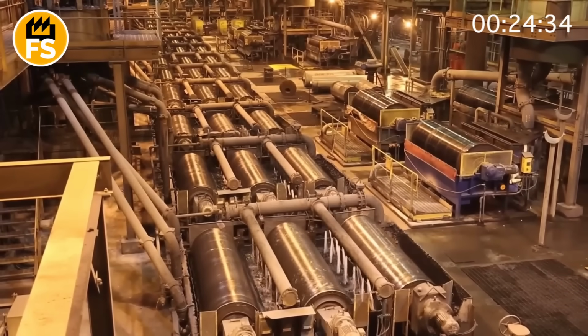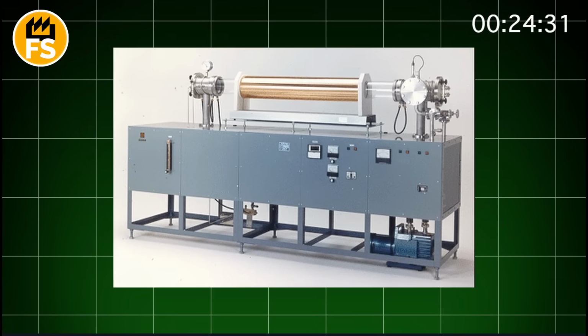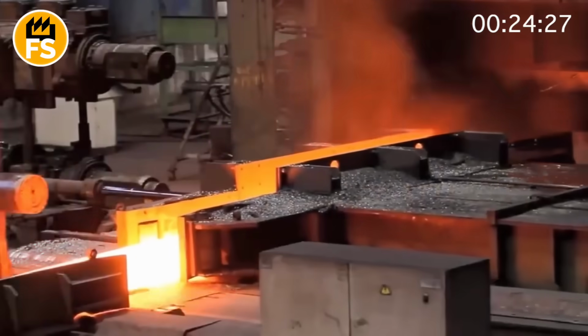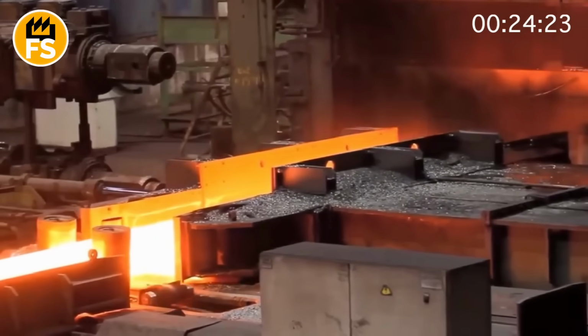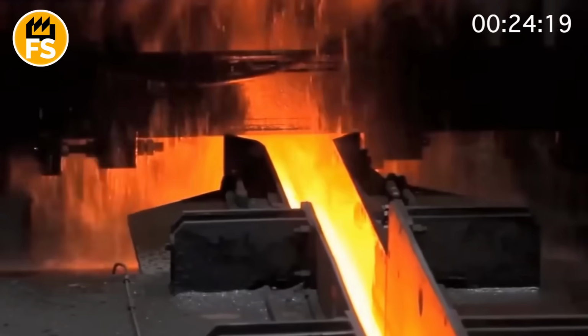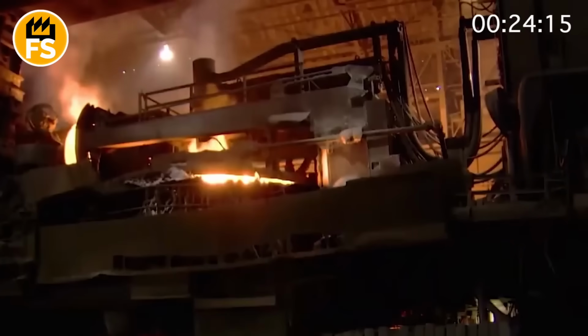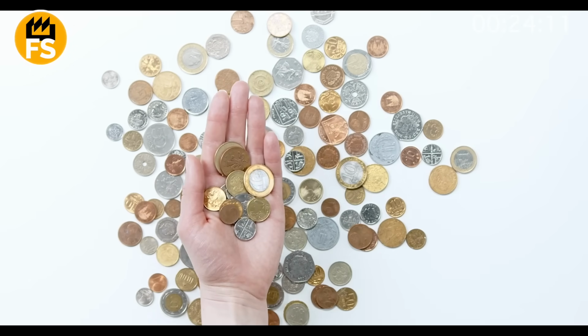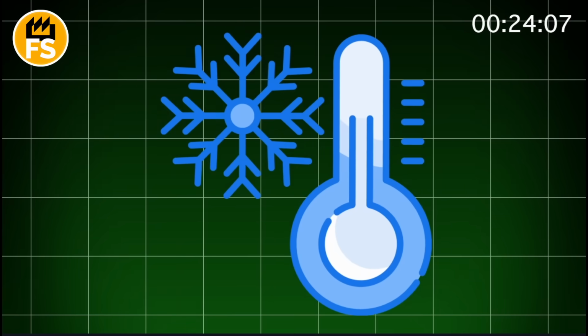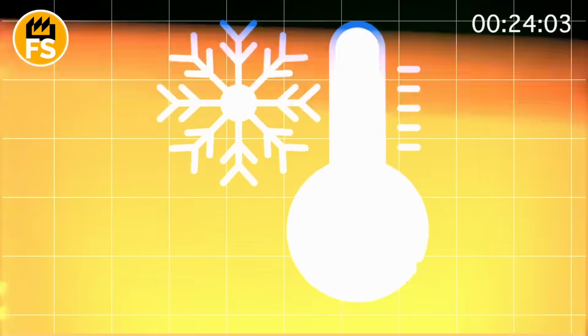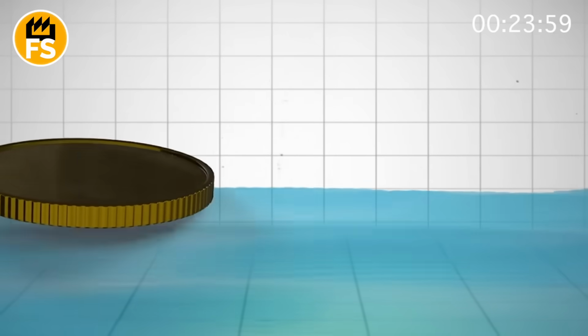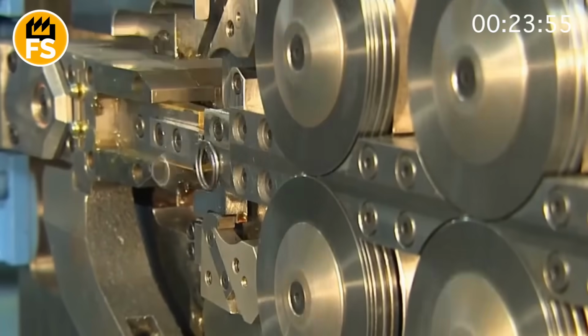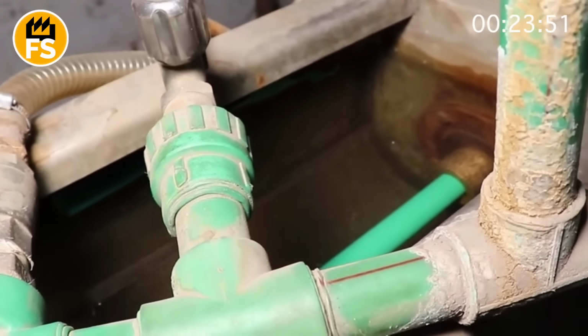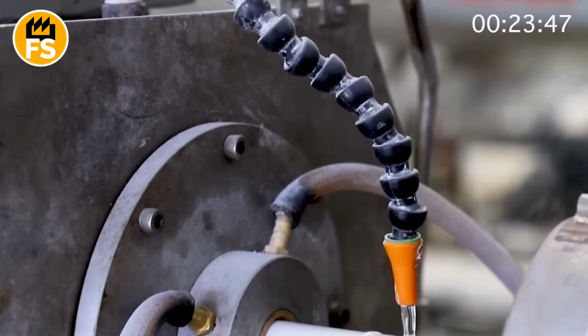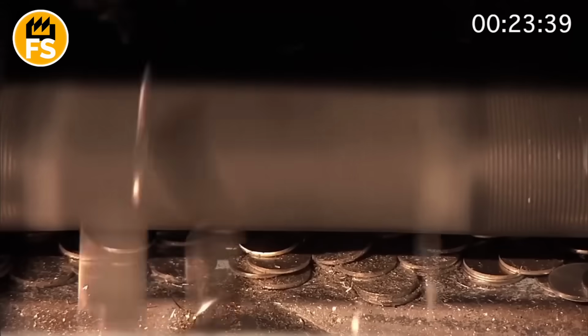Wet blanks are death for stamping. Next, a real fire ritual, the annealing furnace. These metal circles race through a long furnace, 12 to 40 feet long, where the temperature reaches a crazy 1,250 degrees Fahrenheit. The metal becomes red hot, but doesn't melt. It softens. It's like warming up the body before hard work, so you don't tear a muscle. After the furnace comes rapid cooling. The circles fall into a bath of cold water, about 50 degrees Fahrenheit. This temperature shock makes the metal stronger and more elastic. Then the circles are coated with a thin layer of graphite lubricant, so that during stamping, the press doesn't stick or scratch the surface. This is the final cycle of drying and preparation. Now they are shiny, flexible, and ready to take on a pressure of 400,000 pounds per square inch during stamping.